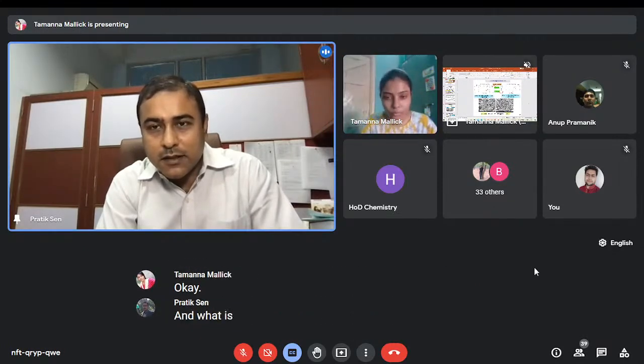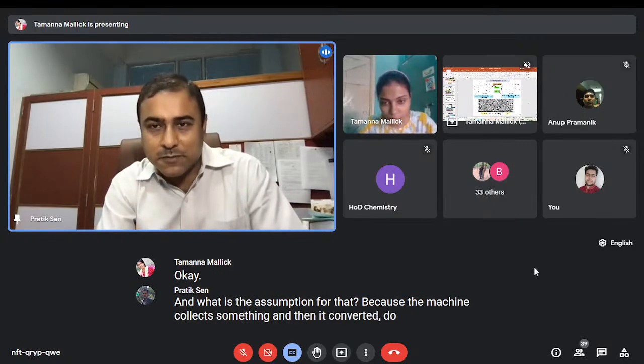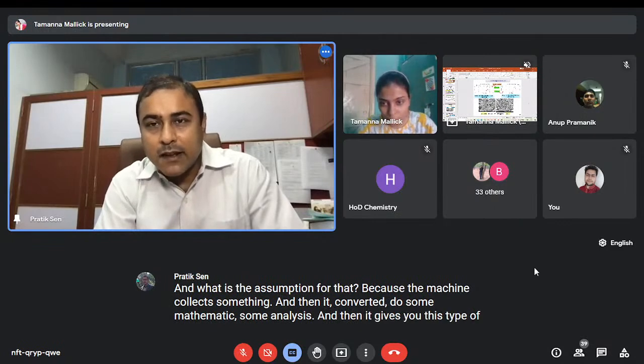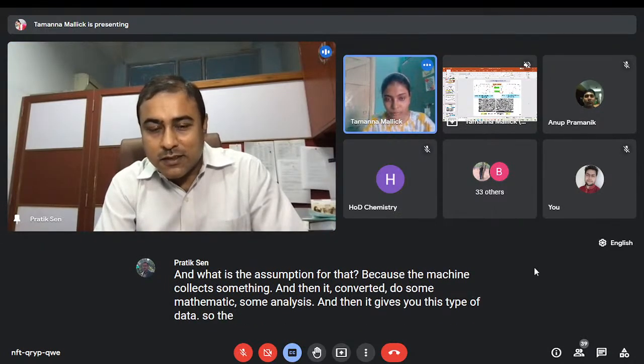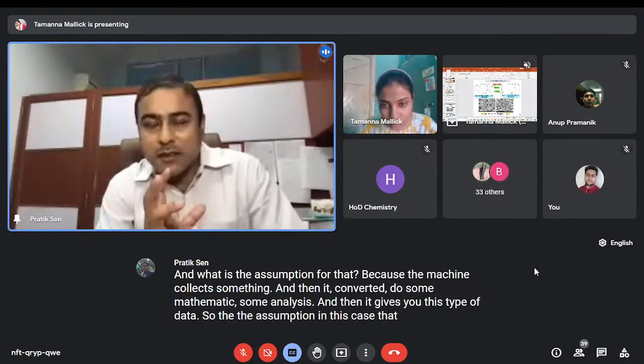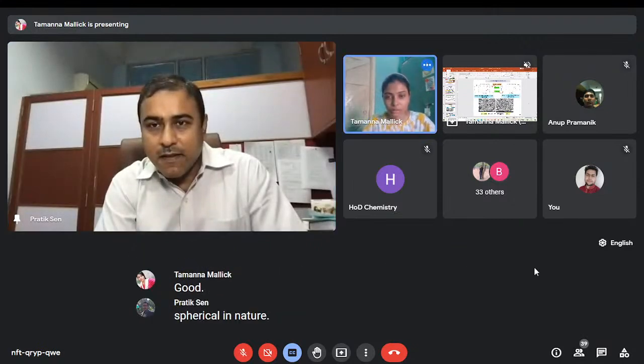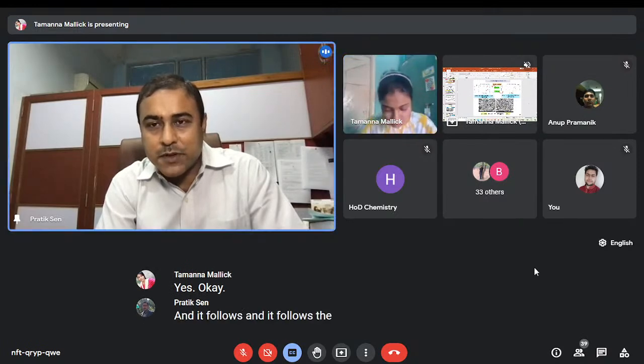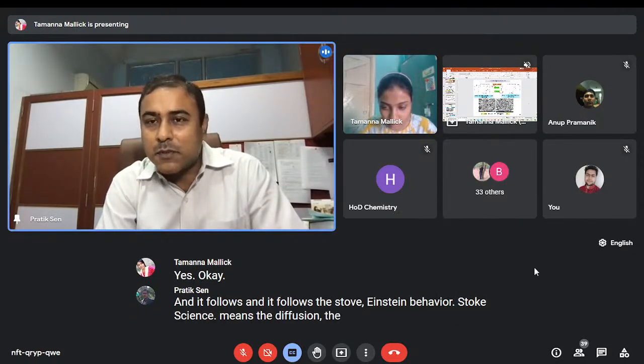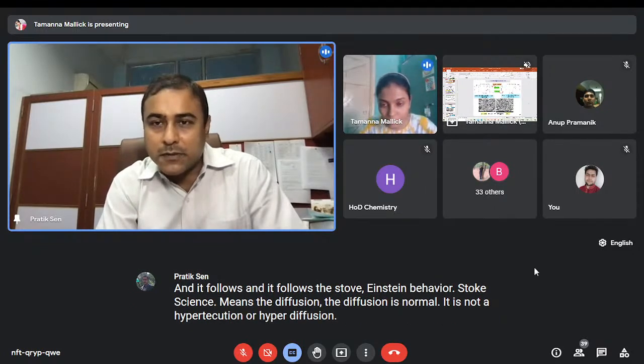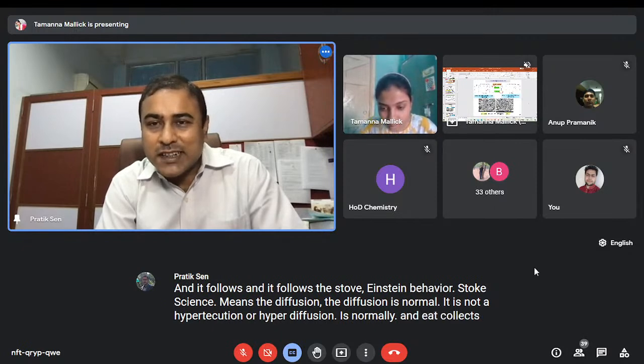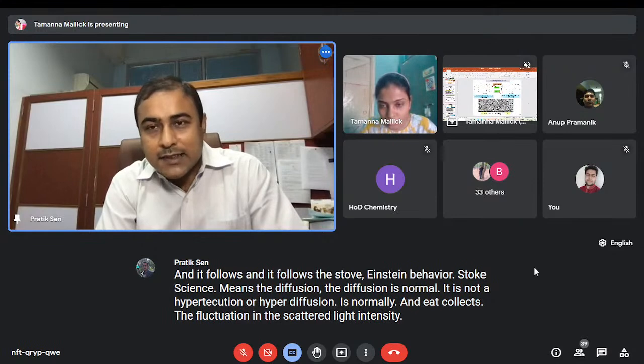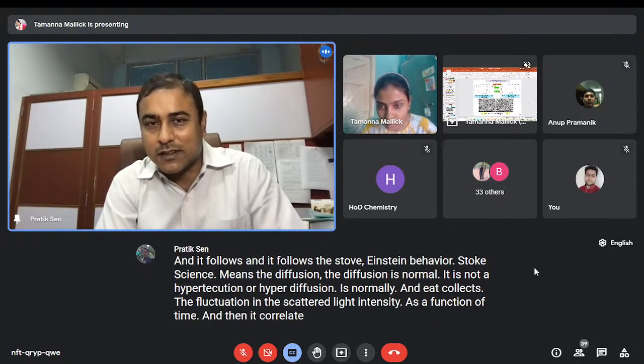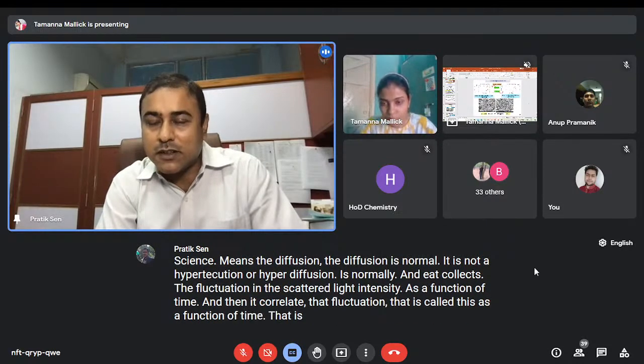Okay. And what is the assumption for that? Because the machine collects something, then does some mathematics and analysis, and gives you this type of data. The assumption in this case is that the particle is spherical in nature and follows the Stokes-Einstein behavior. Stokes-Einstein behavior means the diffusion is normal, not a hyperdiffusion or hypodiffusion. It collects the fluctuation in the scattered light intensity as a function of time, and then it correlates that fluctuation. That's why it's called dynamic.